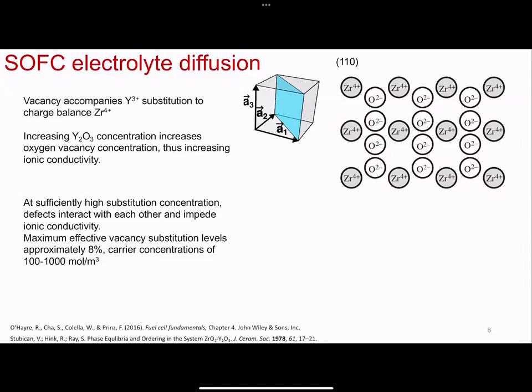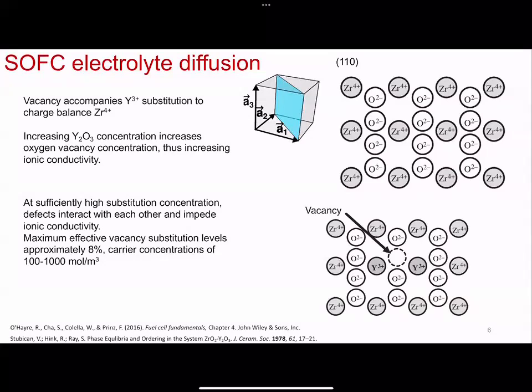Right. So what people have done is they've substituted zirconium, so the cation site, with an aliovalent substitution. What that means is you pick a cation with a different oxidation state. In this case, yttria, so yttrium oxide, or Y2O3. And by substituting with a different oxidation state on the zirconium side, you now also have a vacancy that comes with that for charge balance. So in zirconia, the zirconium is 4+, as you see here, right? So zirconium dioxide: oxygen is 2-, so O2 is 4-, which means zirconium has to be 4+ for charge neutrality. So if you substitute with yttrium 3+, then you need one vacancy for every 3+ to now be charge neutral for 4+. Right, so that's aliovalent substitution.